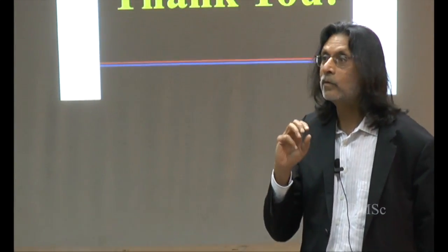So one can use that for rare events. And then there are other approaches. It's very simple. Things slow down when you have to cross very high barriers. If you find out what the energy barrier is, then you know roughly what the time scale is. Then you can start using these accelerated approaches to overcome these barriers and explore the phase space much more readily. So it is possible. But a straight simulation for a millisecond is not possible unless you have a special machine.